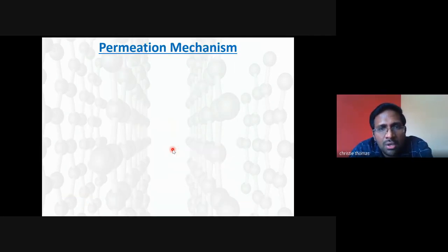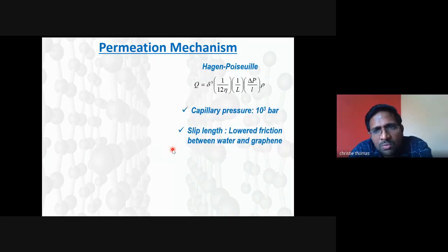Okay, why is it so? Why does water permeate very fast? If you assume standard Newtonian flow and use the Hagen-Poiseuille equation and theoretically calculate the permeation, you won't get a value similar to the experimentally observed value. The experimentally observed value is orders of magnitude larger than the theoretical value.